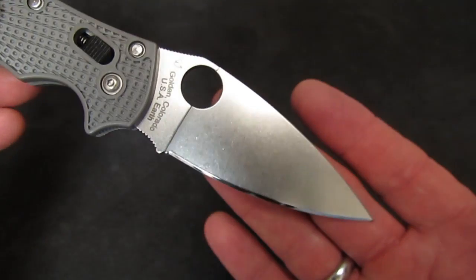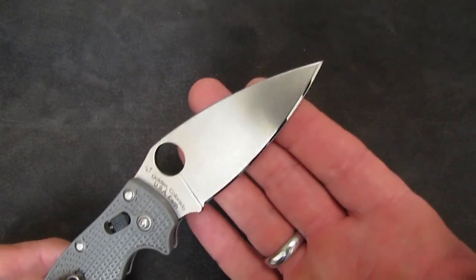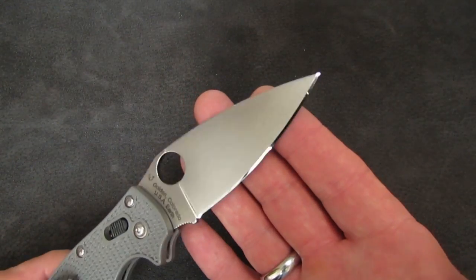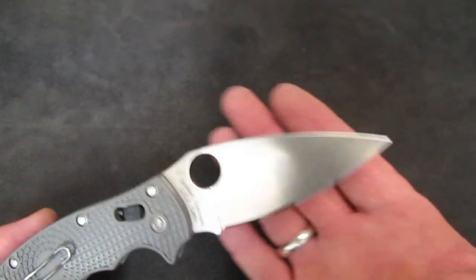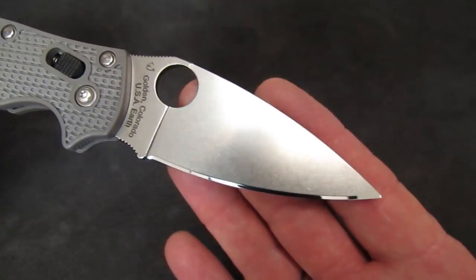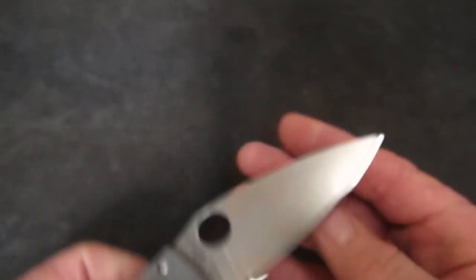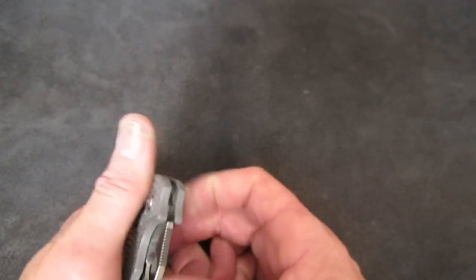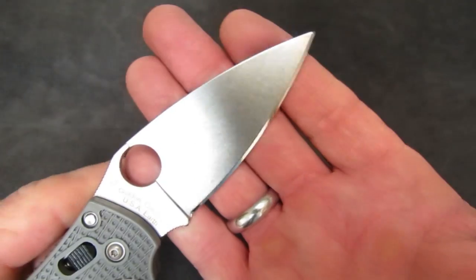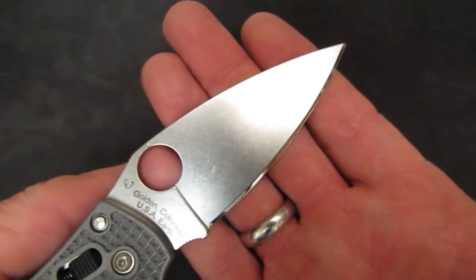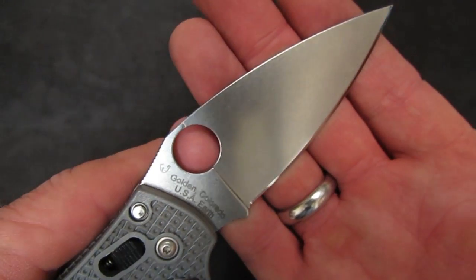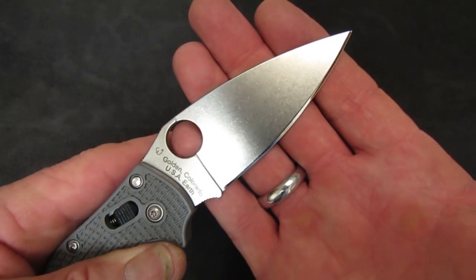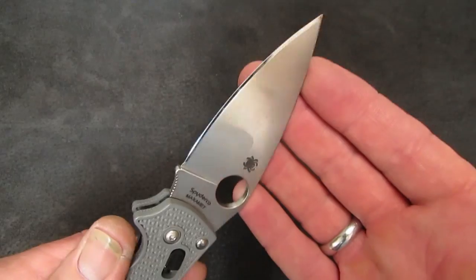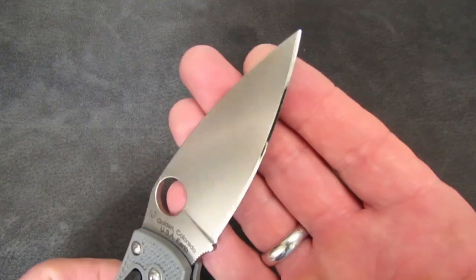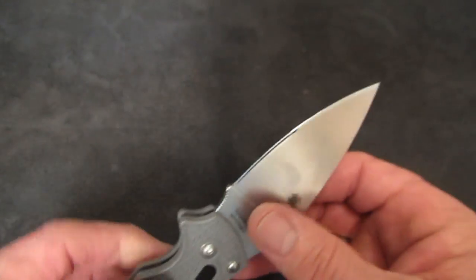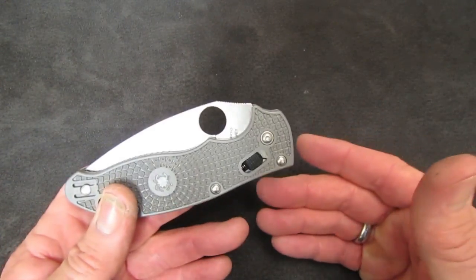The first knife that I did, I thought, surely this is a bad heat treat. And then I started reading about Maxamet, and I found out I wasn't the only one to experience this. Some rather well-respected folks in the world of steels and sharpening, Cliff Stamp, I think, for one. I know that I read Cliff on this steel, and I believe he was talking about edges that needed to be between 25 and 30 degrees per side for Maxamet to have enough stability to be used on a knife.